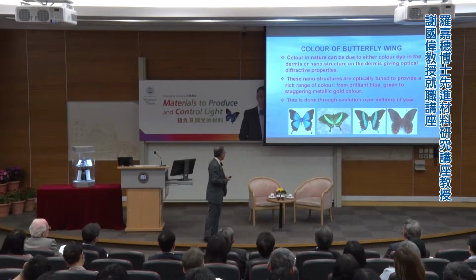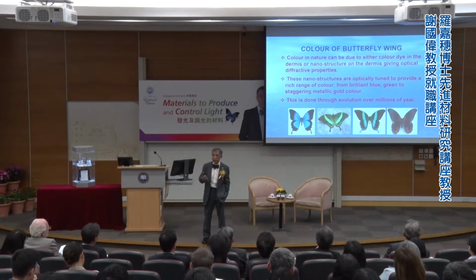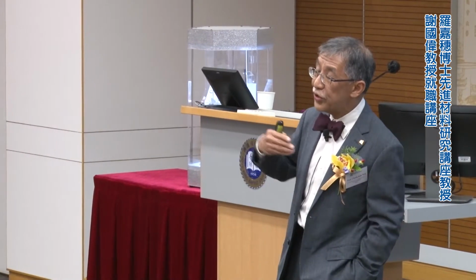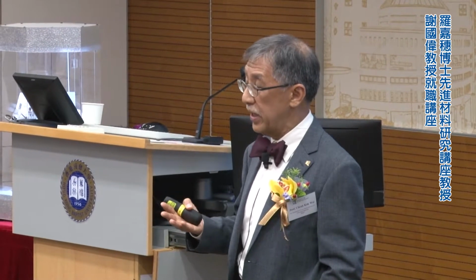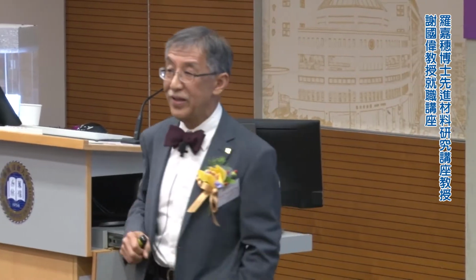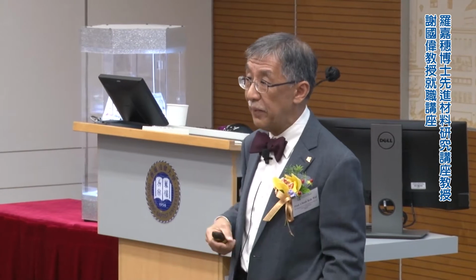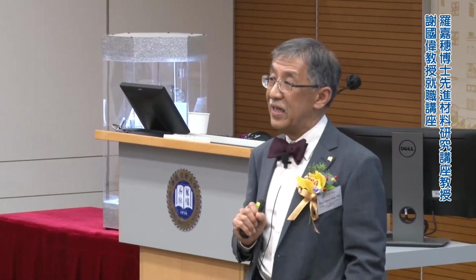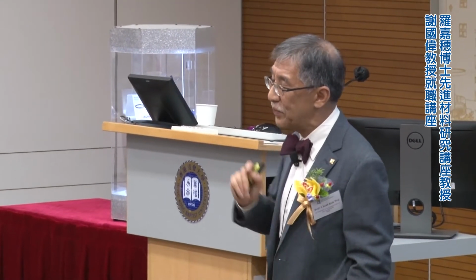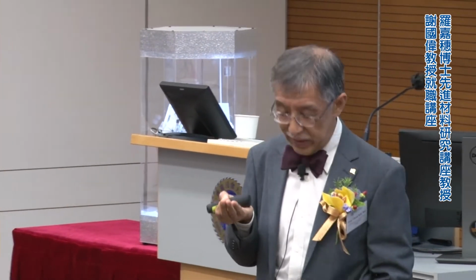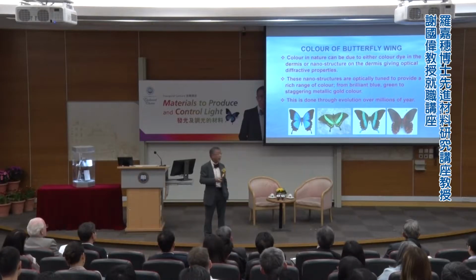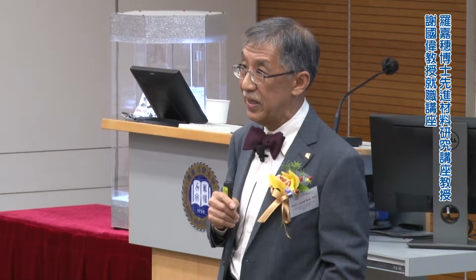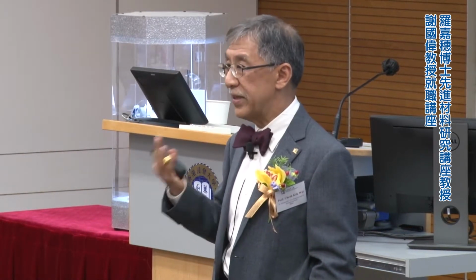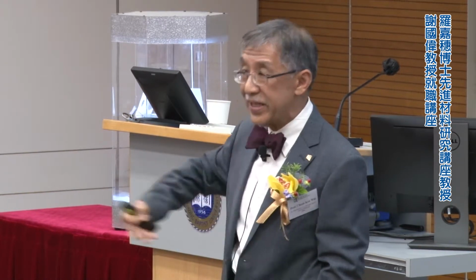And it's very interesting. In fact, this is done obviously through evolution. And when we realized that, I've been asking why, and looked at the regional distribution of that. Generally, we have some understanding. If you're in the tropics and subtropics, near the equator, most of the butterflies will have nanostructures. If you go into temperate regions, like Hong Kong and above, most of them have color dye. I was wondering why, and then I found a possible answer. Because the sun is strong at the equator, it's very bright, so using a nanostructure to reflect color is more efficient. Also, the sun being bright, we all get sunburn, you have UV. And UV light will destroy your dye. So the butterfly will spend a lot of energy replacing it all the time.